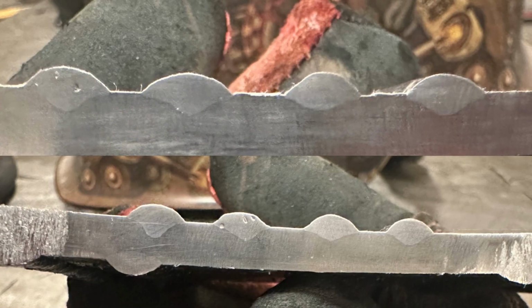Now here's both of them side by side. It's pretty interesting how in one section you can have no porosity, and then in another one, just a millimeter ahead, you have a bunch. That's just the nature of it. Based on this small scale testing, I would say that running gas shielding with C25 will actually limit the penetration, but it does give you a reduction in probable porosity, at least based on what I'm seeing.